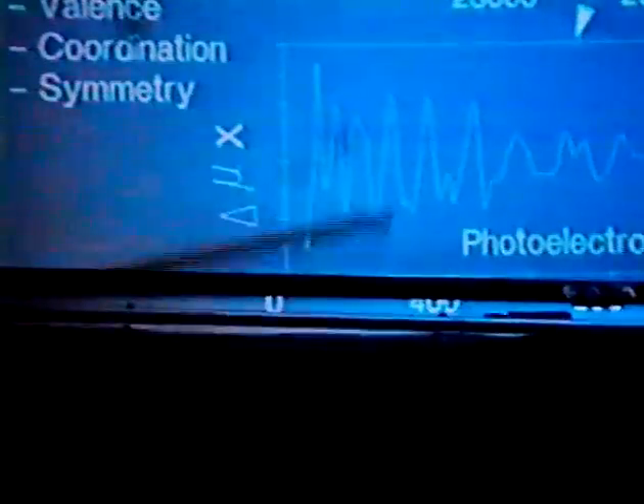But the modulation is basically a scattering pattern. And that being the case, then, the interpretation of this thing, which is really a scattering pattern, is fairly straightforward. So what do I have written here? Oh, so what we're looking at here is scattering of a photoelectron backscattered by the local environment of the absorbing atom. Next slide.